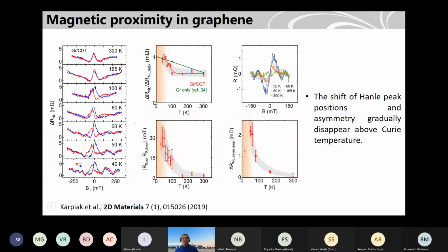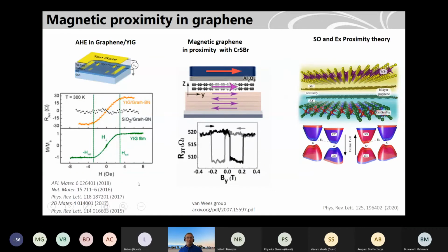And that we see with the temperature dependence curves. As you see, the splitting decays when you go to higher temperature. And surprisingly, we find that at the interface the Curie temperature is quite a bit higher than in the bulk sample. That can happen, and people have found in other systems that such proximity can also affect it.